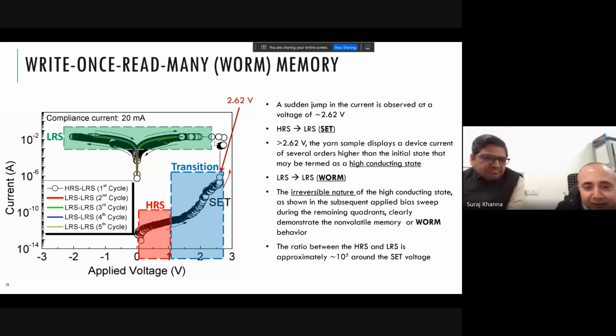So I would state again to all the audience, it is generally pretty okay to go with the conservative way of testing the material, but at the same time you have to be very careful to understand your material fully. Because you may not intend your material to be conductive in some particular application, but if it happens to be excited by the correct voltage, it can turn into conductive. Okay, so that's the main takeaway